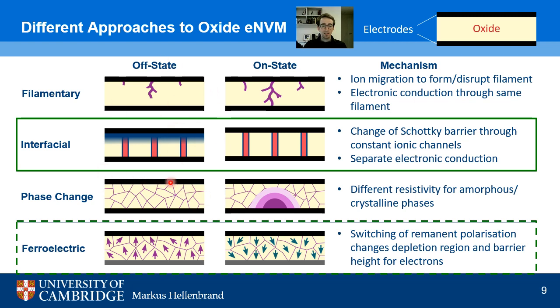Another very popular approach besides these two is making use of the difference between electronic conduction in a crystalline and an amorphous material. So if you remember from one of the previous slides, the atomic configuration inside a material can be crystalline or amorphous, and the electronic conduction in these different states will be different. So let's say we have a higher electronic conduction in a crystalline material and a lower electronic conduction in an amorphous material. So then by changing between the two states, we can again represent our 0 and our 1. This is typically induced by heating up the material locally. So you can see if there was a heater down here, we can crystallize the material going out from this heater and thus change the electronic conductivity between the two states.